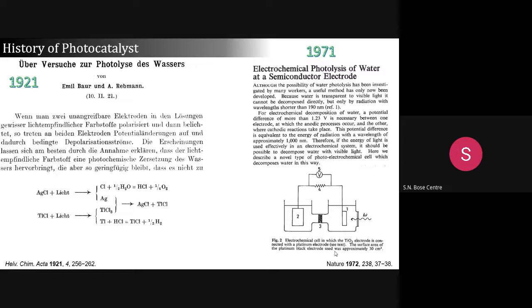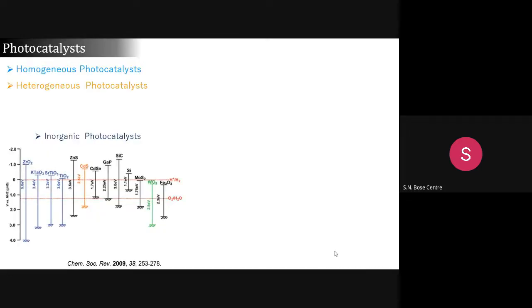Almost 50 years later, Honda and Fujishima, everybody knows about this paper, used a photoelectrochemical setup to produce hydrogen. Here they used a platinum electrode and a TiO2 electrode as a photoactive electrode, and then they excite it with light, which produces an electron, and the electron goes to the platinum, which produces hydrogen. After that, chemists started exploring different kinds of materials, not only TiO2, and they explored almost most of the periodic table elements and produced different oxides, sulfides, nanoparticles, and other things for water splitting.